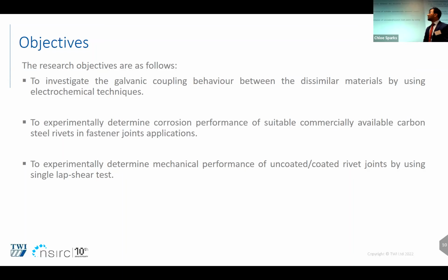And the second one will be to experimentally determine the corrosion performance of suitable commercially available carbon steel rivets and fasteners for joint application. That will be the standard commercially available coatings, and to determine the mechanical performance of uncoated and coated rivet joints by using the single lap shear test. So this one is the uncoated one and the coated one. The coated one includes the commercially available as well as the one that I'm going to coat with different coating techniques and different coating materials.